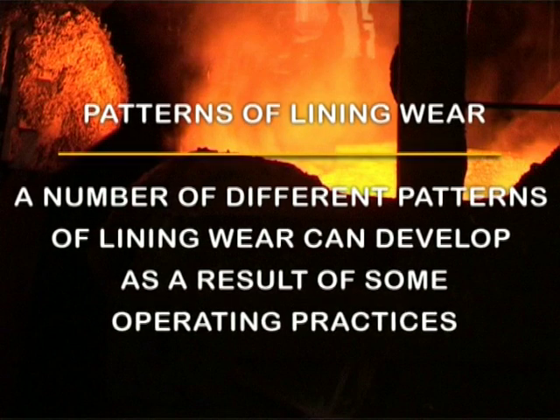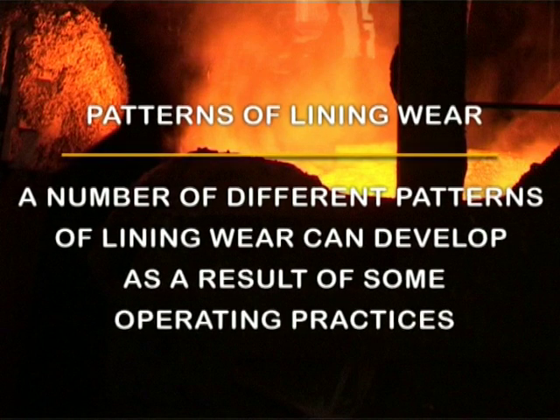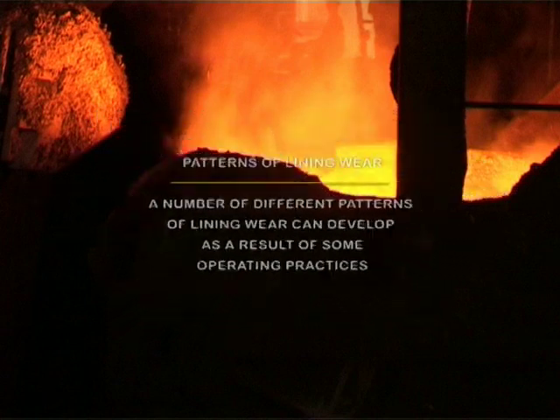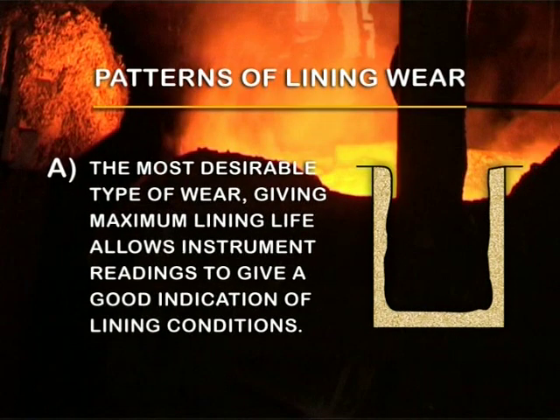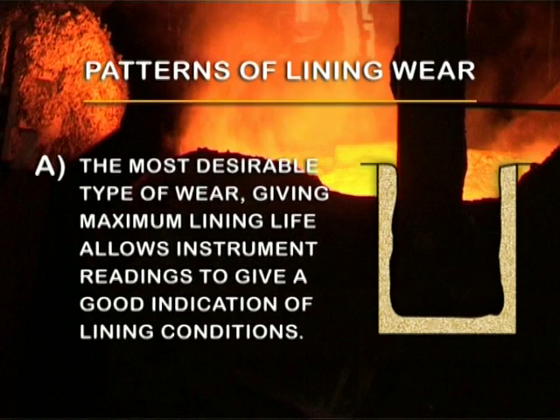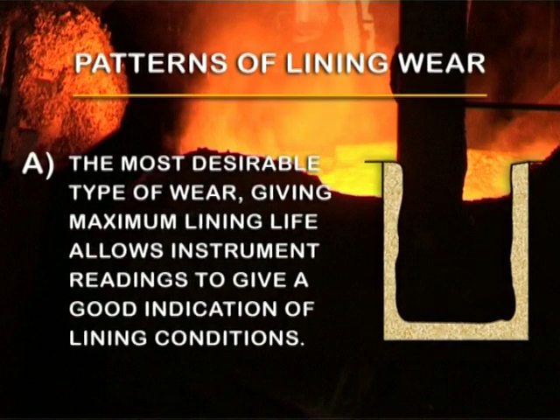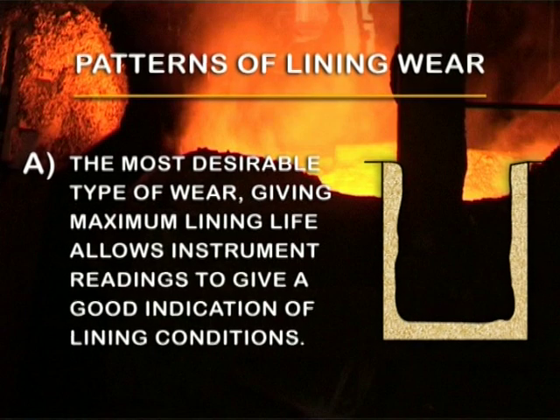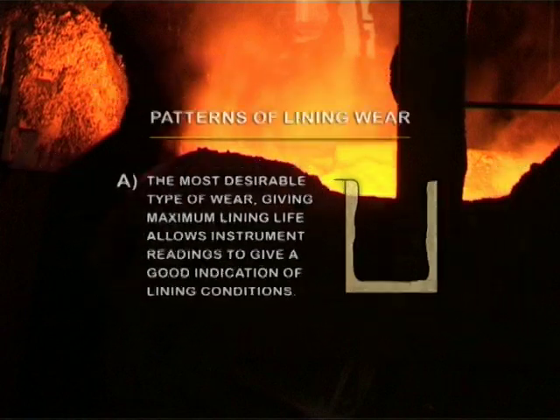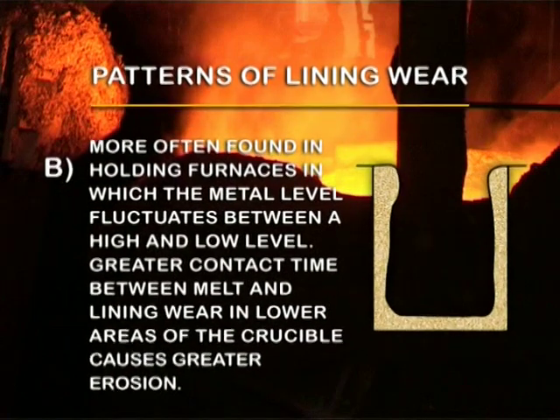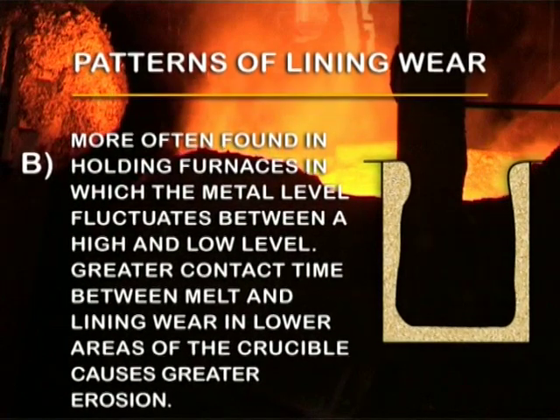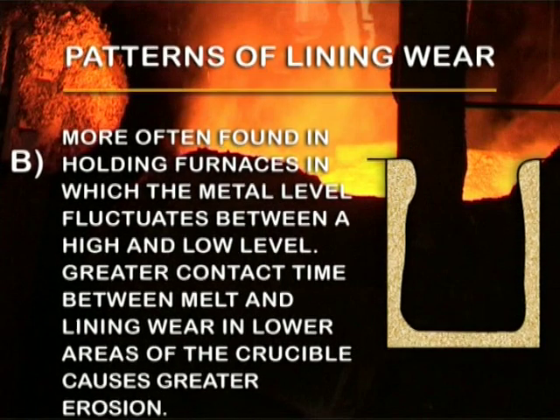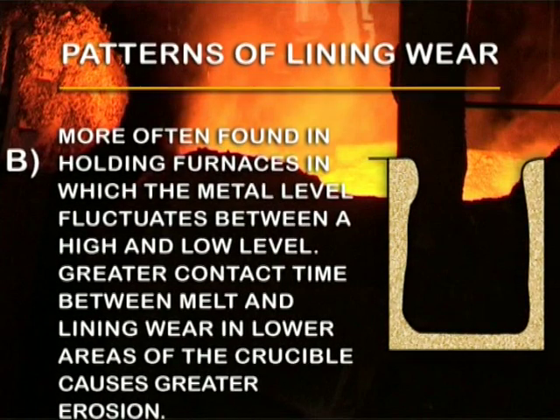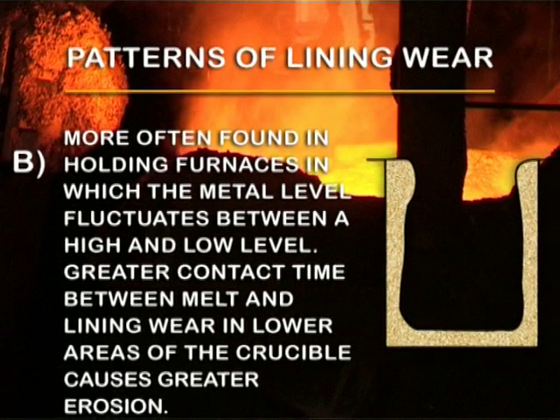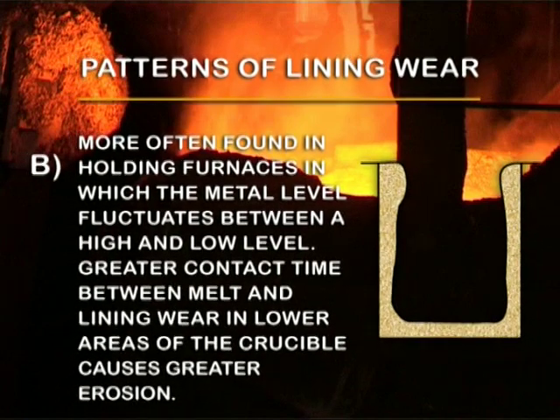A number of different patterns of lining wear can develop as a result of some operating practices. The most desirable type of wear, giving maximum lining life, allows instrument readings to give a good indication of lining conditions. More often found in holding furnaces in which the metal level fluctuates between a high and low level. Greater contact time between melt and lining in lower areas of the crucible causes greater erosion.